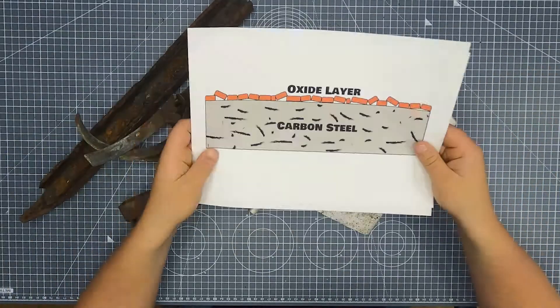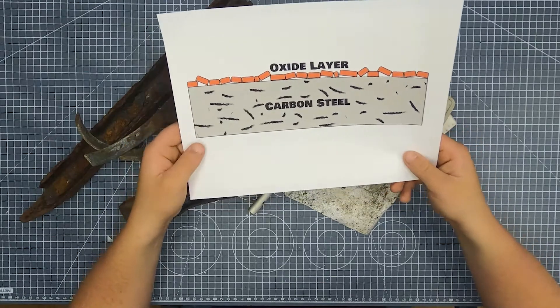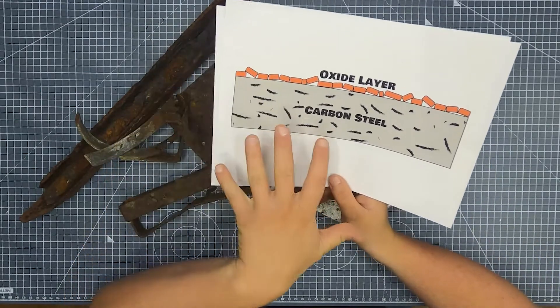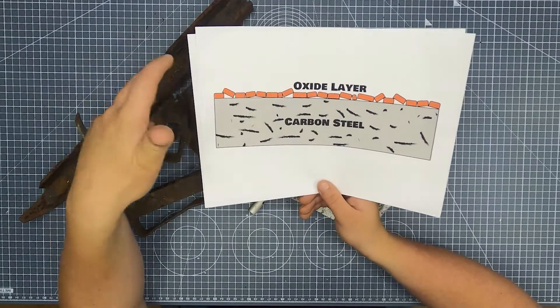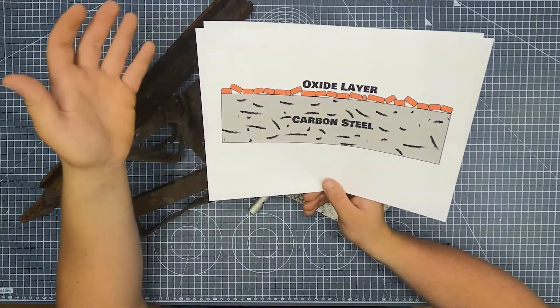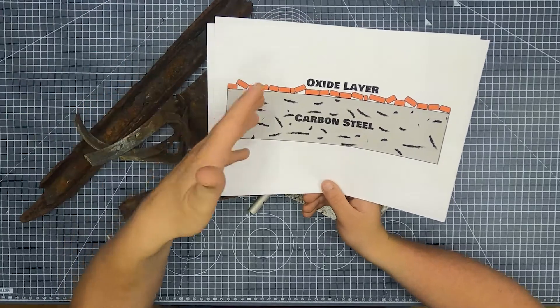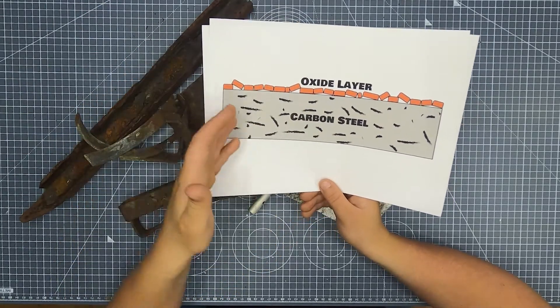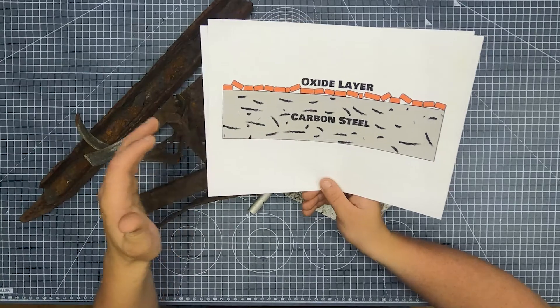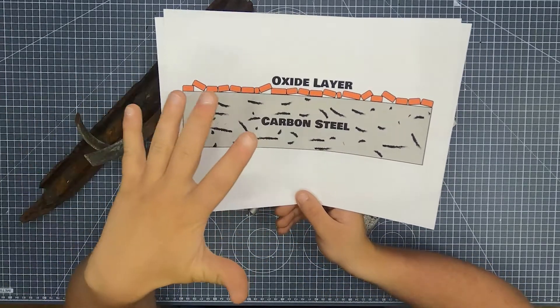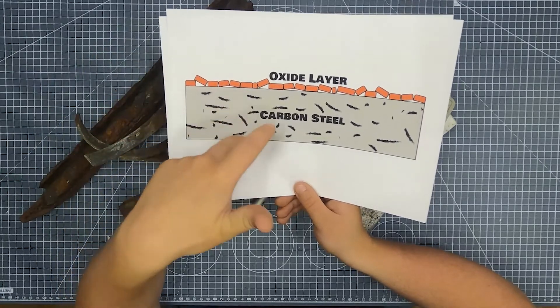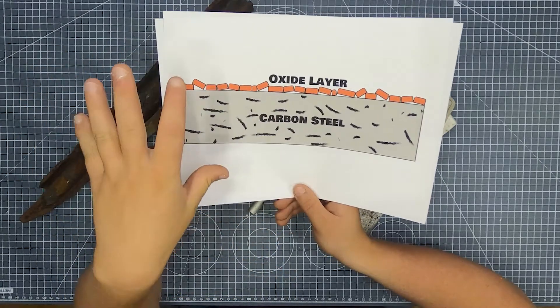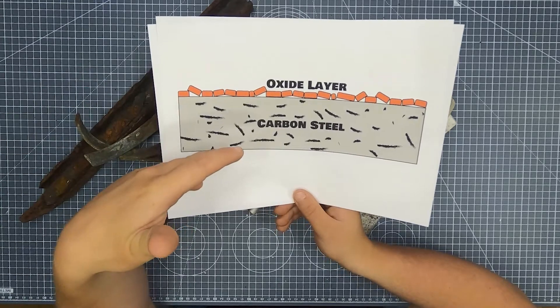On the other hand, steel's oxide layer is over twice the size of the base steel. So as the oxide layer is growing, huge stress is formed because there's more oxide there than there is space. So it causes it to crack and flake off. These cracks leave the bare face of the carbon steel open to the air and open to the elements, open to moisture and this allows the corrosion to continue layer by layer and doesn't provide much if any protection at all to the steel underneath.